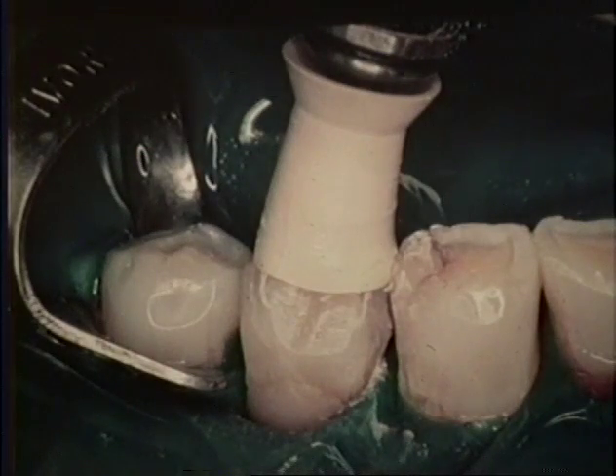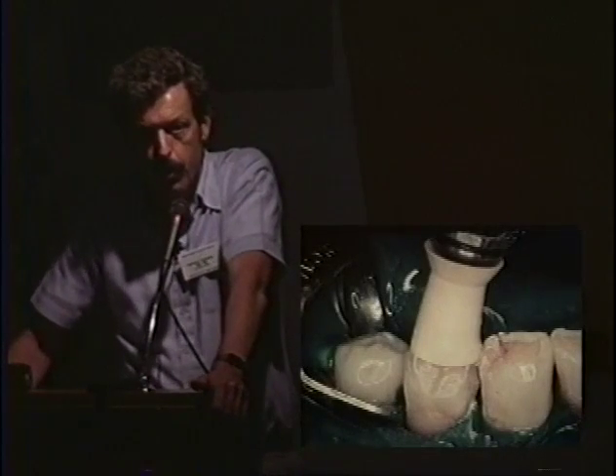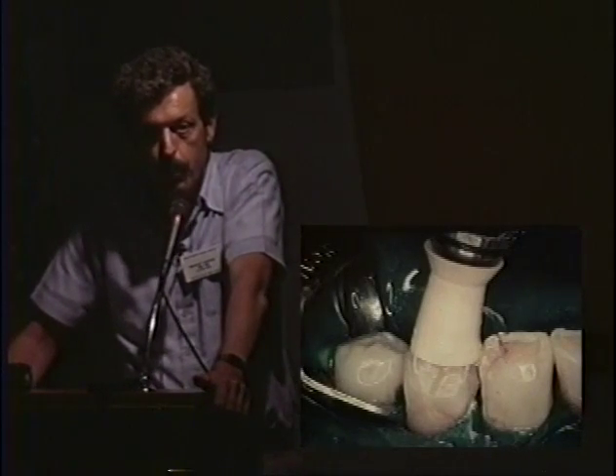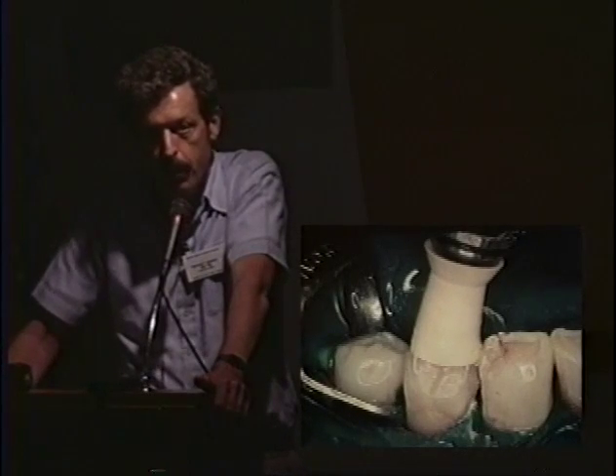Now Helio will polish with Prophy paste to a pretty good finish. Coarse Prophy paste, and then of course change the cup or wash the cup thoroughly in fine Prophy paste. That's a pretty good finish, and I would find it clinically acceptable. If you want to take it to another stage of polishing paste, well, that's fine, no problem. But you have to ask yourself in your practice now, if you're going to take it to, say, Prismagloss as a final stage, what about your dental hygienist? Do they routinely use Prismagloss, or do they rip through there with coarse Nupro Prophy paste? In my experience, they rip through with coarse Prophy paste, because coarse Prophy paste outsells fine Prophy paste by 25 to 1.